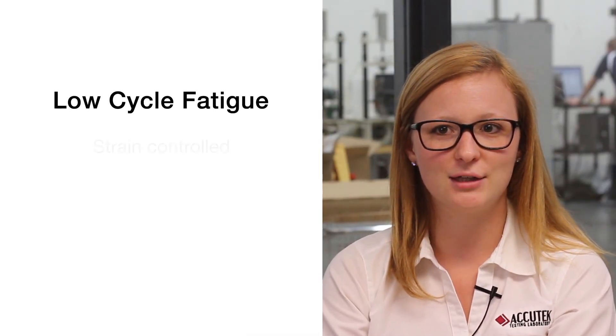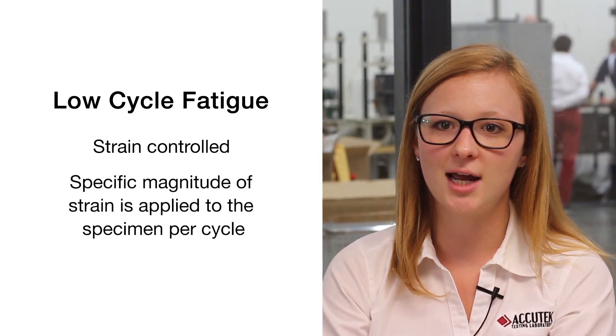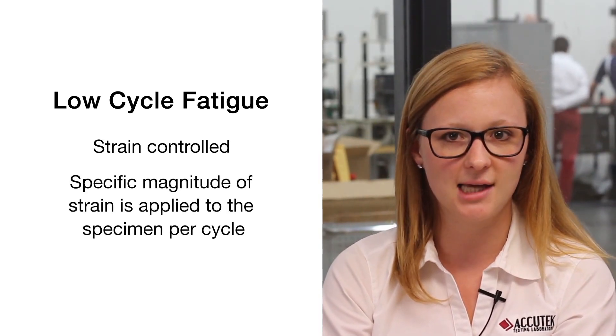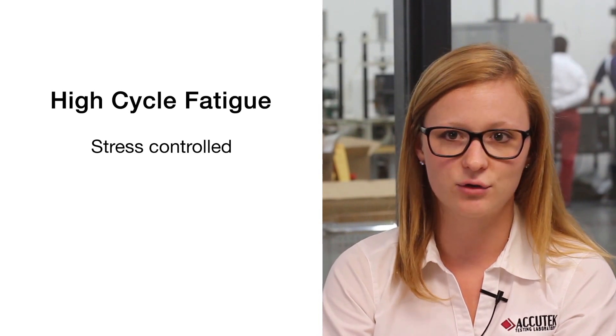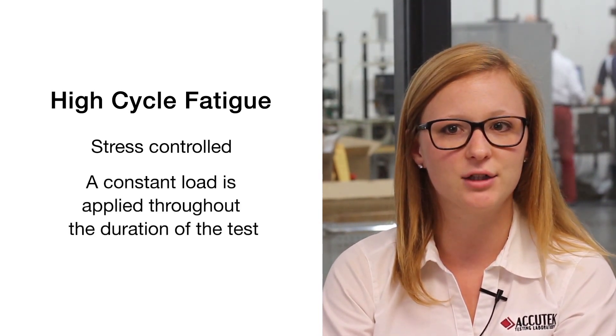Due to material behavior at low stresses versus high stresses, both methods are performed using different control methods. Low cycle fatigue is performed using the strain control method, where a specific magnitude of strain is applied to the test specimen per cycle. Traditional high cycle fatigue is stress controlled, meaning a constant load is applied throughout the duration of the test.